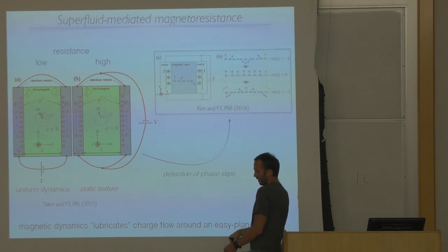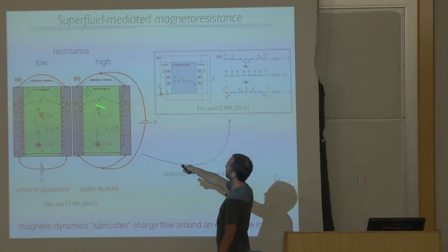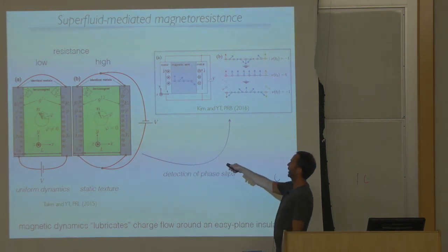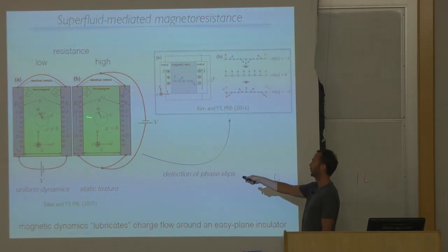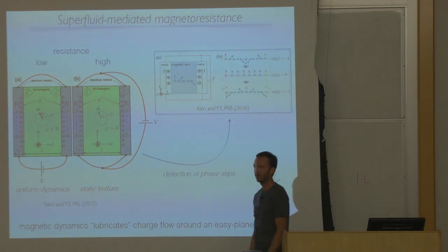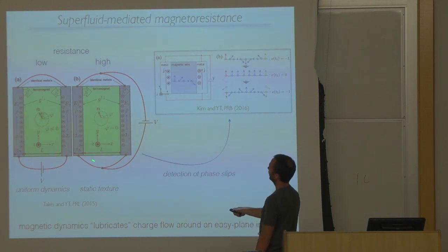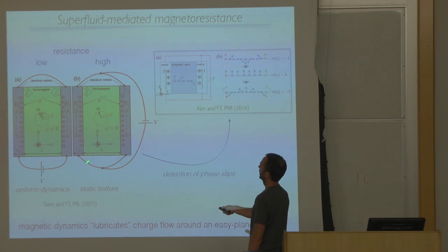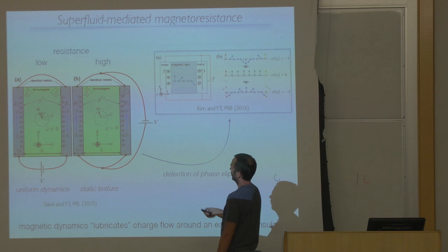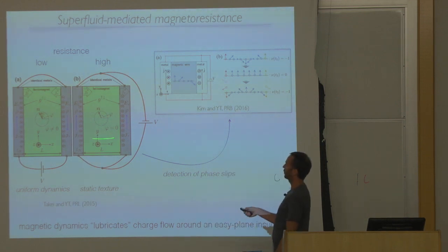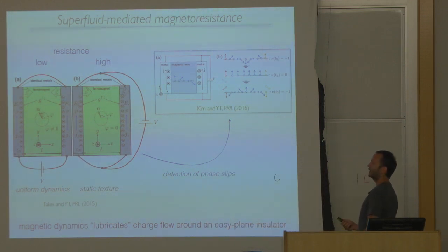So in the steady state, we simply have a static spiral with this injected and drained spin current being basically proportional to the gradient of the phase in between. And you would really not measure anything when the dust settles. This magnetic texture is static. So from the point of view of these metallic wires, you basically see no dynamics. So the metals would not pick up any kind of electromotive force from this magnetic dynamics unless you have phase slips. Okay, and you will have phase slips.